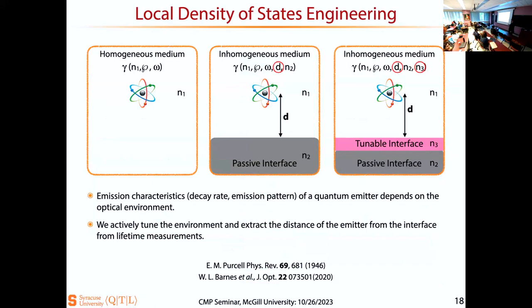Okay, so to really explain how we did it: if you take a single atom in the excited state, the decay rate does not depend on the surroundings; it's a quasi-intrinsic property. In free space, a linear homogeneous medium, it's an intrinsic property. But the moment you break the homogeneity, the decay rate depends upon the dipole orientation. Like the famous example we all see in undergraduate, a dipole in front of a perfect conductor, or just gold. An X dipole behaves differently than a Z dipole. So this is what we harnessed.